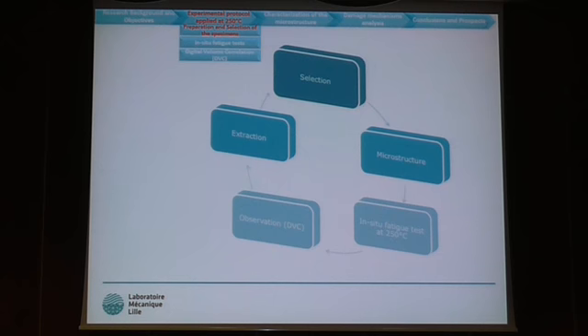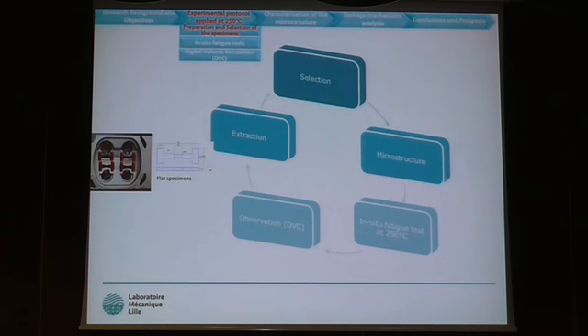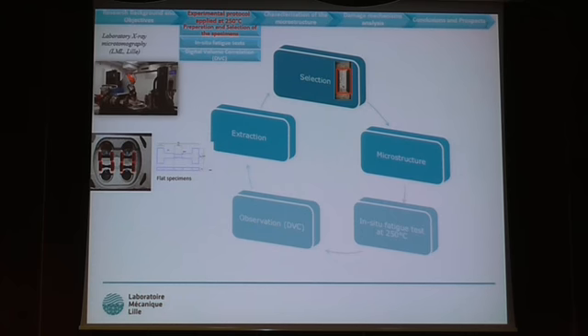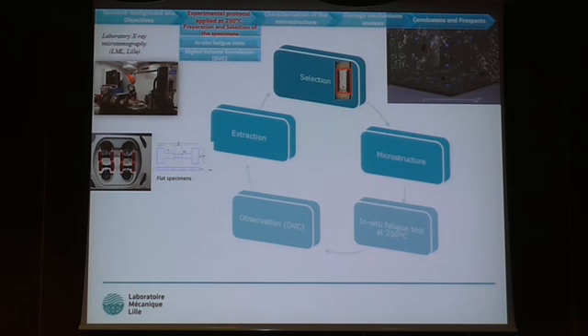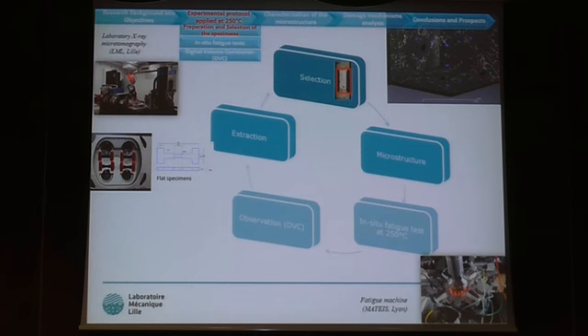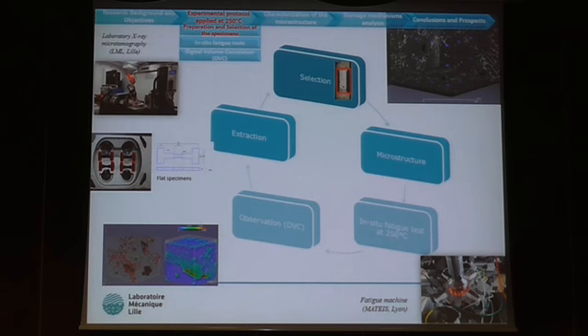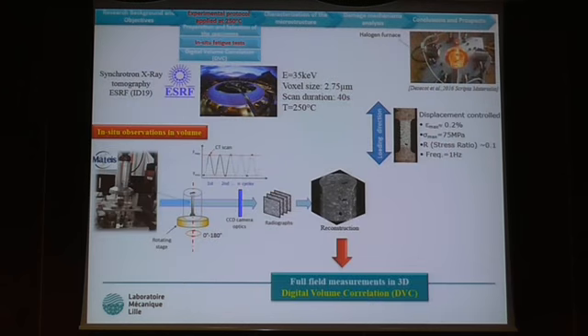So for that we developed an experimental protocol. The first step is to extract flat specimen from the cylinder head. Then you need to select a good specimen. What I call good specimen, it's specimen with all the defects, all the porosity in the area of observation, which is the central zone here. For that you use laboratory X-ray microtomography, and thanks to this tomography image, we can characterize in 3D the microstructure. Then we perform in situ fatigue test in high temperature. And finally, we can observe the crack initiation and crack propagation in 3D, thanks to digital volume correlation.